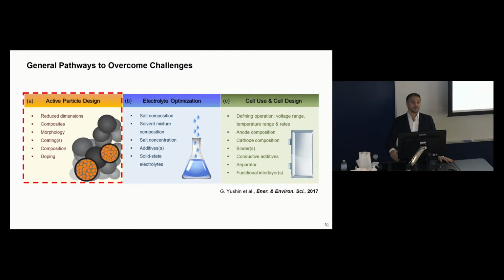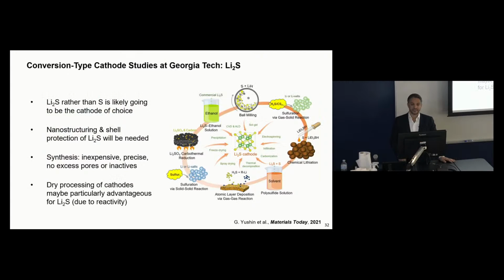And particles, I think, is the most attractive approach because everything else can be kept the same, kind of a drop-in replacement, as I mentioned. And so, as I mentioned, there are two candidates for conversion-type cathode materials that probably have the future. One is sulfur-based, lithium sulfide, and another one is metal fluoride-based. So you can use the sulfur-based cathode in a lithium-free state, right, as sulfur, a very cheap material, or you can use it in a fully lithiated state as lithium sulfide, Li2S.